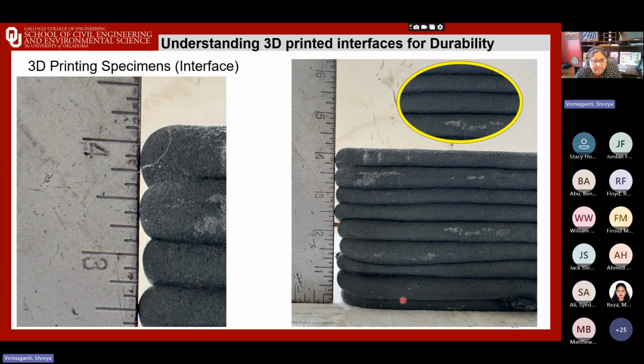You can see there are still some irregularities in printing, but just by observation, you can identify some weak seam lines, right? And the bond quality of these joints dictates the structural performance. So it could fail prematurely, but it could be designed also. In our case, we want to put reinforcement in these interfaces. So you see some subtle gaps. There's also some roughness during the deposition that can be seen, which could help in friction. But over time, what we saw is how these interfaces, when you place the reinforcement in there and subject it to chemical ingress, what could happen at these interfaces.